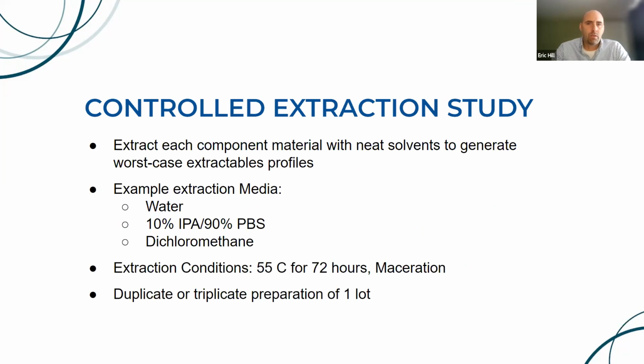Once we've documented what sort of patch we have and what the materials and components are, we're going to move into what's called a controlled extraction study. And this is defined very specifically in USP 1663. So each component material is going to be extracted with neat solvents. That's going to generate a worst case extractables profile. Some example extraction media that we may employ, depending on the chemistry involved, could be water, 10% IPA, 90% PBS solvent, and then dichloromethane. Those three solvents give us a range of chemistries, a range of polarity, so we can get a full extractables profile of those materials. Typical extraction conditions could be 55 degrees C for 72 hours. Usually this is extracted under maceration conditions. Maceration generally means soaking conditions. And we would advocate for duplicate or triplicate preparation of one lot.